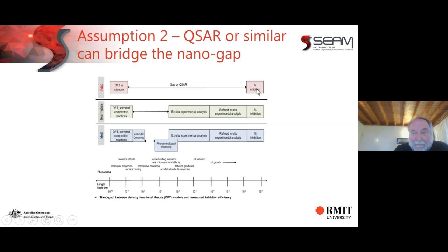Generally, we measure inhibition either on an exposed plate, which is 100 by 150 millimeters, or on an electrochemical coupon, which is a bit smaller, but still 20 mils, which is much bigger than our DFT experiments. We could do refined analysis, local analysis on our features, and we could also expand our DFT modeling to try and close that gap.